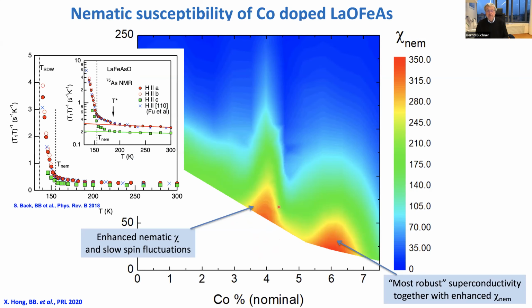That there is a coupling, we know, of course. We know, for example, from NMR measurements, when you go to the magnetic phase or the nematic phase transition, you see a strong enhancement of 1/T1T, so a strong slowing down of spin fluctuations. So there is certainly a coupling between nematicity and spin fluctuations. And if the magnetic transition becomes very unstable close to the quantum critical point, with enhancement of spin susceptibility, you can also expect something going on in the nematic fluctuations. That's what I think is going on here.